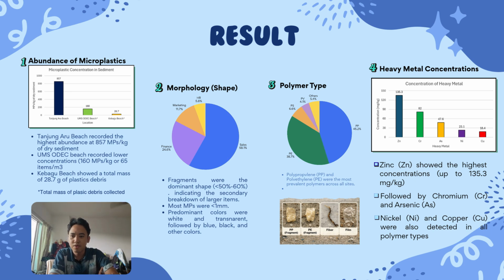Moving on to morphology characteristics, fragments were identified as the dominant shape, accounting for approximately 50 to 60% of the particles collected. This suggests that many of the microplastics originate from the breakdown of larger plastic material through environmental processes such as sunlight exposure, wave action, and physical weathering. Most particles were smaller than 1 mm in size, indicating advanced fragmentation. In terms of color, white and transparent particles were the most dominant, followed by blue, black, and several other colors.